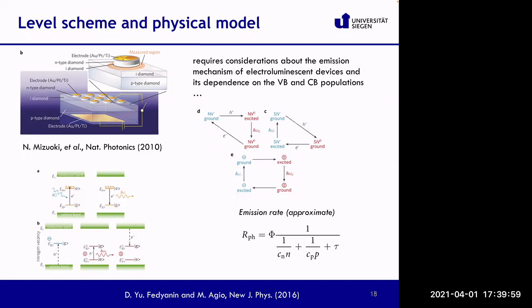And then you have in the denominator of this equation 3 different contributions. So tau is the spontaneous emission. So this is the typical term that you have also by optical pumping. And then you have 2 other terms that are related to the capture process of an electron and the capture process of a hole. So Cn and Cp are the capture cross sections, and N and P are essentially the electron and the hole density that you can have in the conduction and